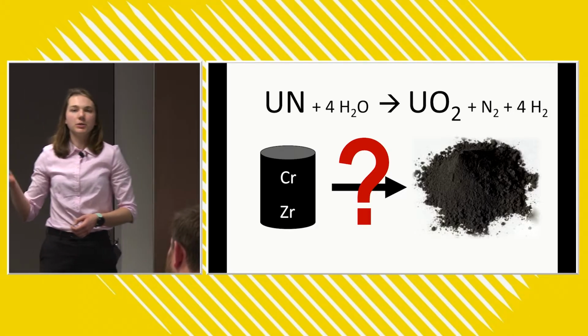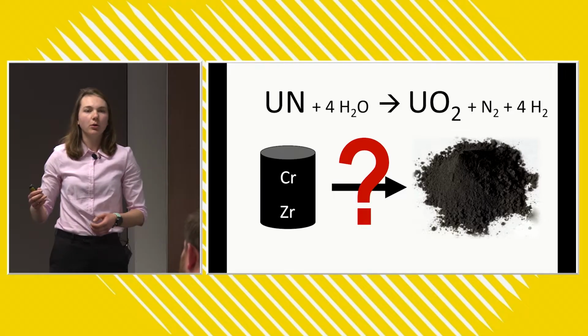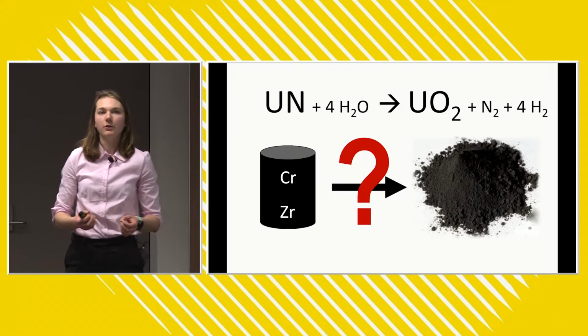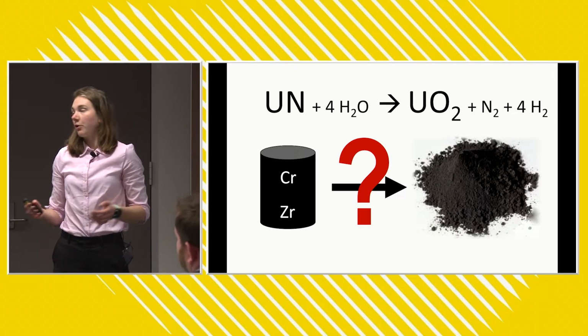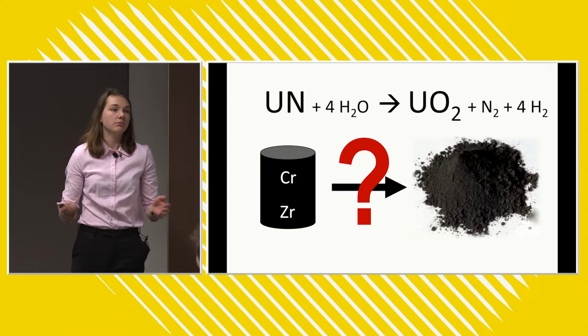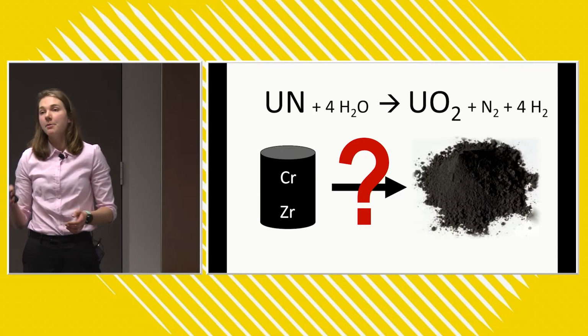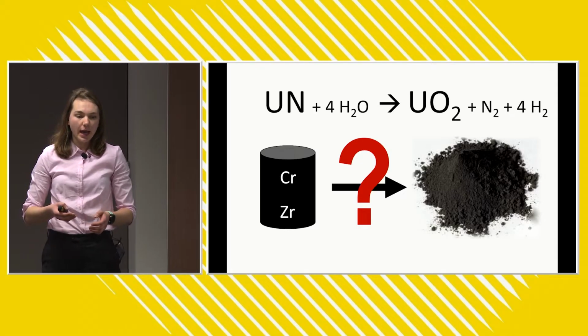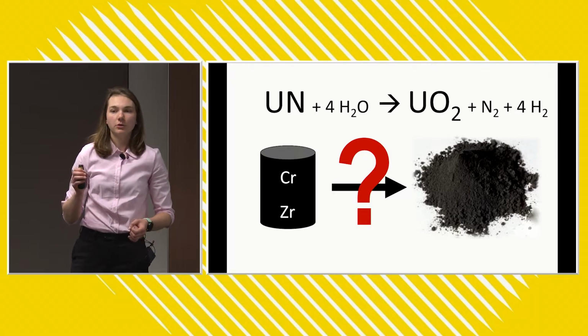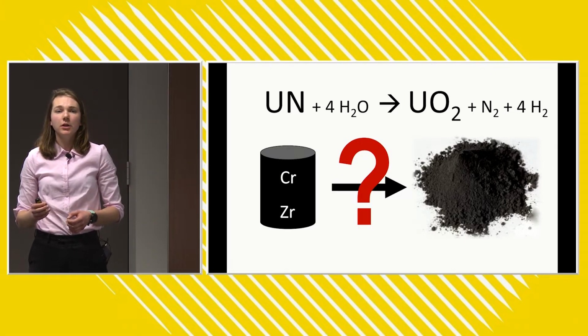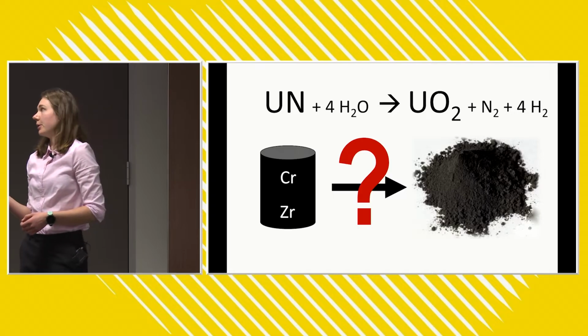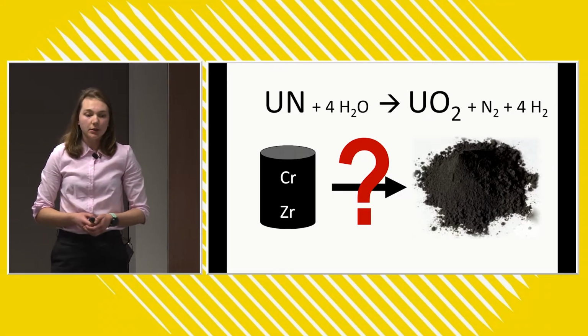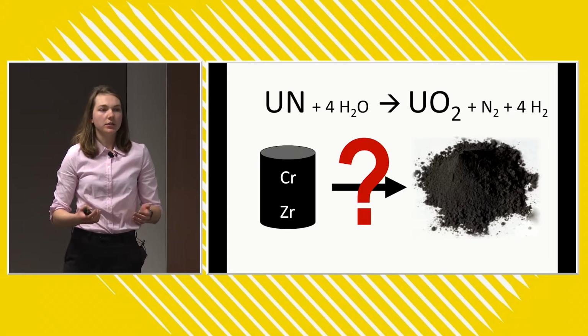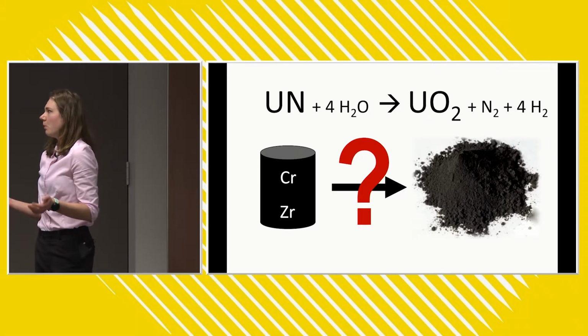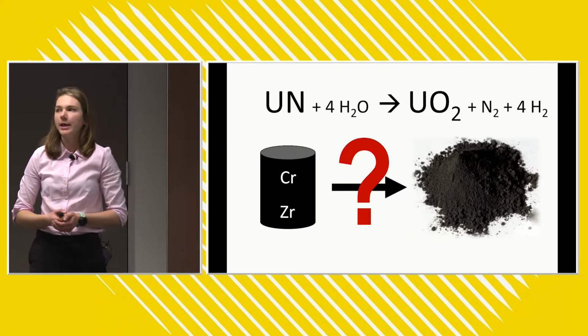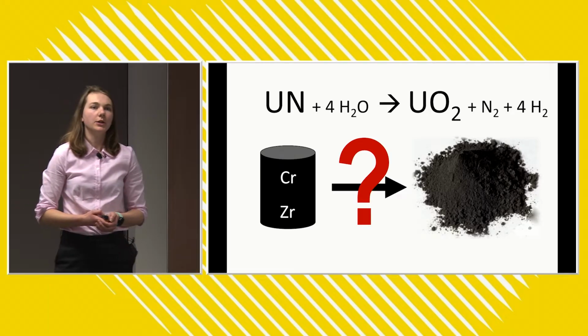And that's really important because with that technique, we can then explore ways of improving the corrosion properties of uranium nitride. So chromium, for example, is widely used in many materials to improve the corrosion resistance. But interestingly, in this case, chromium has been found not to improve the corrosion resistance of uranium nitride upon exposure to steam. And instead, if we add zirconium, it does. So, why is this? And some of the results that I'll show later will tell us why that's the case.